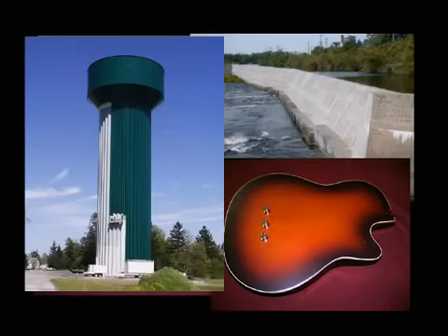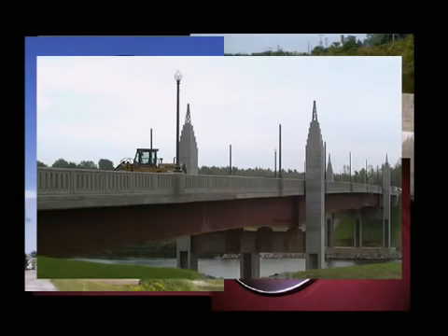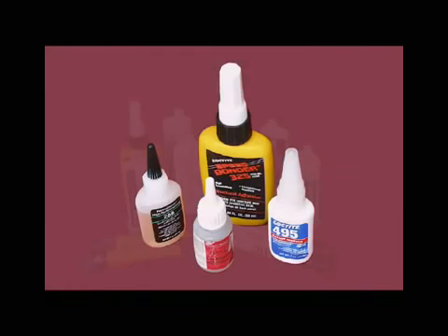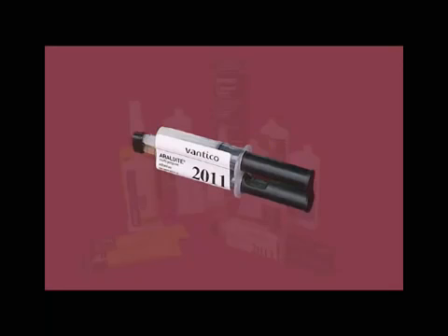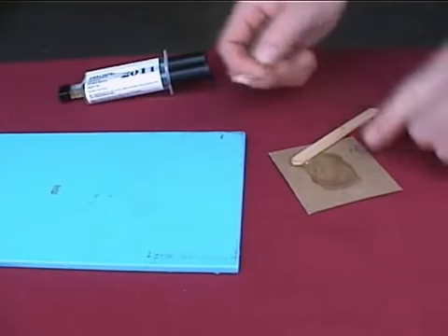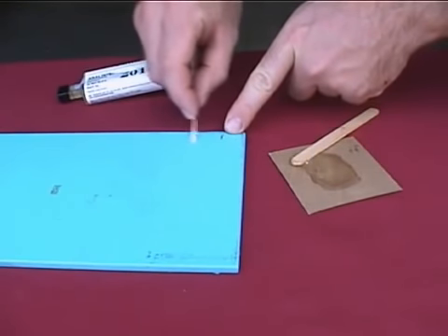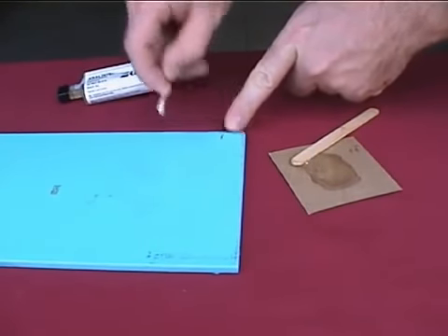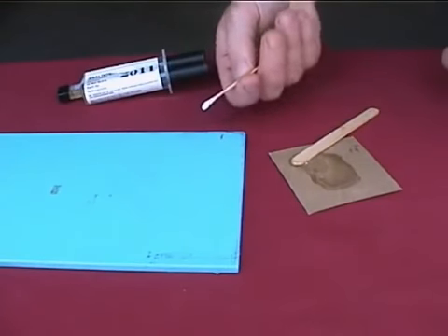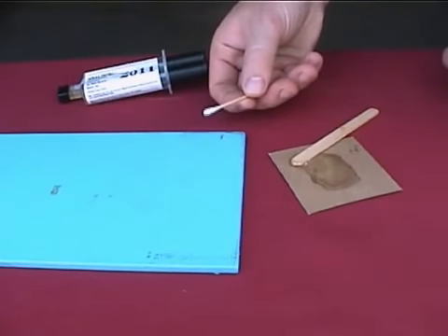For applications under 7 megapascals, 1,000 pounds per square inch, or when a fast-curing adhesive is required, cyanoacrylates, superglues, are commonly used. When stronger bonds are required, it is recommended that a two-part epoxy be utilized. Several manufacturers utilize Araldite 2011 epoxy due to its versatility. Warning: with any adhesive selection, it is important to test and ensure that the adhesive does not react to the coating, resulting in a change in its cohesion properties or bond strength.